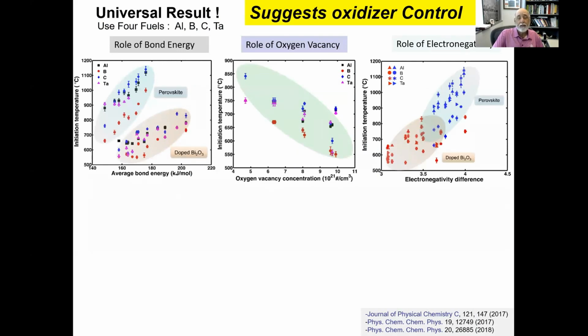Now, is this generic? I've shown you everything for aluminum, but now I'm going to do boron and carbon and tantalum. So I'm going to now make it for a whole range of fuels. Here is ignition temperature versus average bond energy. And this is all the data for perovskites. For each family, the black ones are the aluminum, red is boron, blue is carbon. You can see that they follow the same trend.